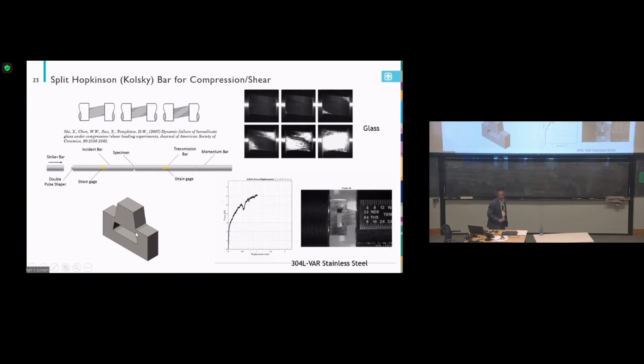Now we see how the specimen got fractured and the force displacement. So you can see it's already playing here. My subject to the top hat, you got a compression shear on the interface over there. Then it went to totally fractured. Now we have load displacement. But all of this work tries to validate material models, because they use a uniaxial stretching curve. They put the material model in, do the simulation. How do we believe their model is correct? So we gave another problem. What about you simulate this and compare with our experiment results? If it matches, yeah, I believe you. So that's how we do the material model validation process.